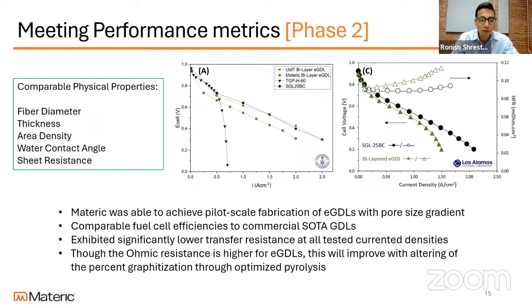And eventually we were able to produce and meet the physical properties that they wanted in terms of fiber diameter, thickness, and areal density, and also meet some of the electrochemical specs that they were looking for in terms of current density, voltage, and resistance. The material that we produced also had significantly lower transfer resistance at many tested different current densities, which further bolstered our claim into translating into the pilot line scale.